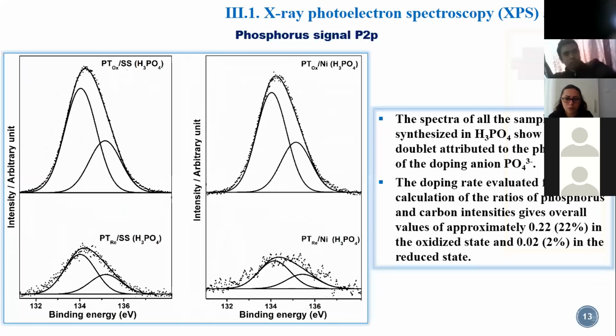The spectra of all samples synthesized in phosphoric acid show a single doublet attributed to the anion doping. Doping rates are approximately 20% in the oxidized state and 2% in the reduced state. For the polymer synthesized in perchloric acid, 2 doublets are observed in the oxidized state. The first is assigned to the chlorine atom, and the second comes from the presence of the perchlorate anion. After reduction, this doublet disappears almost completely following the expulsion of the counter anion. Estimated doping rates are around 15 to 20% for oxidized films and between 0 and 1% for reduced samples.